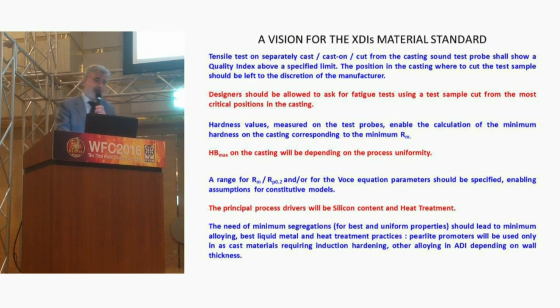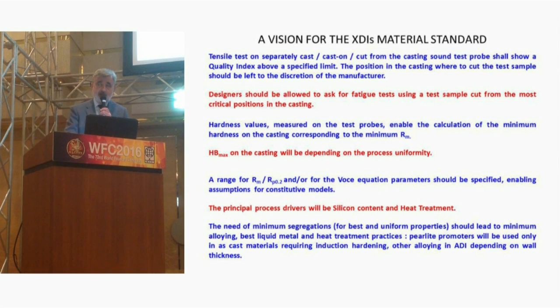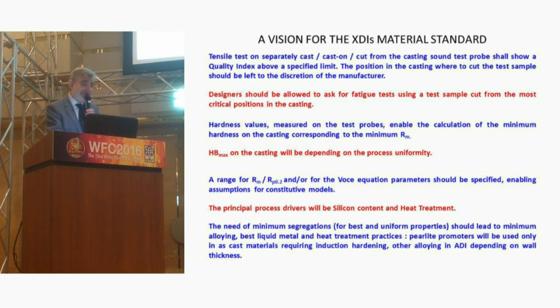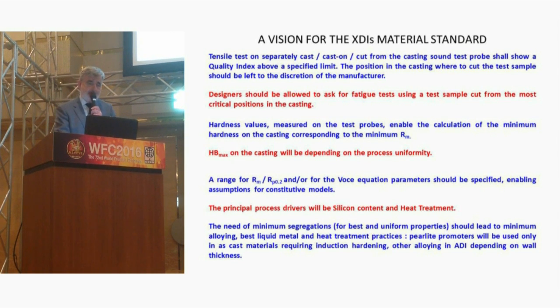So my vision is that the tensile test of a separately cast or cast-on test probe shall show a quality index above a specified limit, as I showed before. The position in the casting where to cut the test sample should be left to the discretion of the manufacturer to be sure it will be sound, but designers should be allowed to ask for fatigue tests using a test sample cut from the most critical position in the casting.